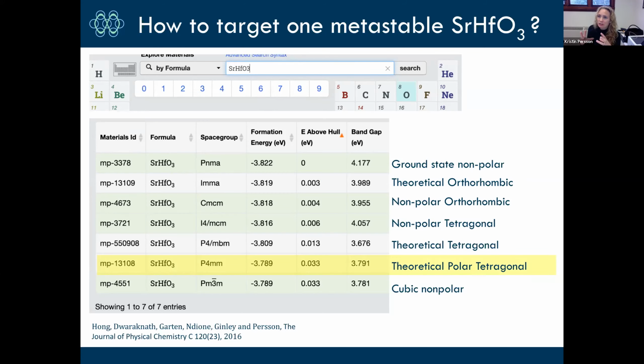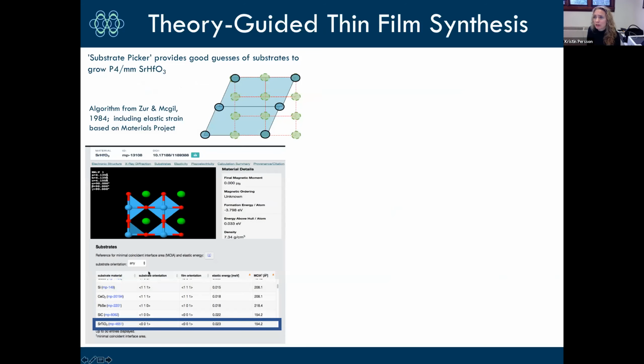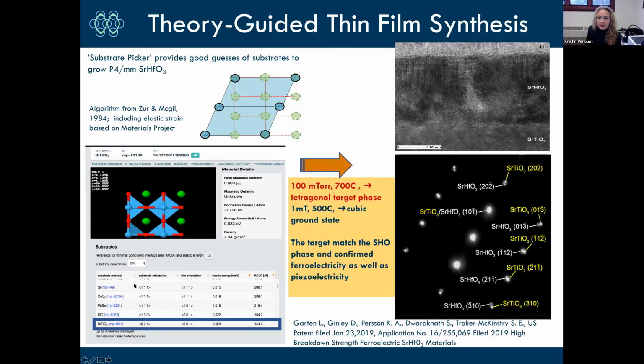This means that you have to tailor and really tune your synthesis conditions to this particular polymorph. The NREL team were experts in epitaxial growth. So we tried to see whether we could tailor the substrate specifically to penalize those lower-energy polymorphs and promote this particular one. And we actually used computations to do that as well. We looked at the lattice mismatch of the more stable polymorphs versus the one we wanted to make with existing substrates. And we were able to see that one particular strontium titanate substrate that we doped with niobium would skew the energetics slightly, such that our film should be more energetically favorable if we templated on this substrate.